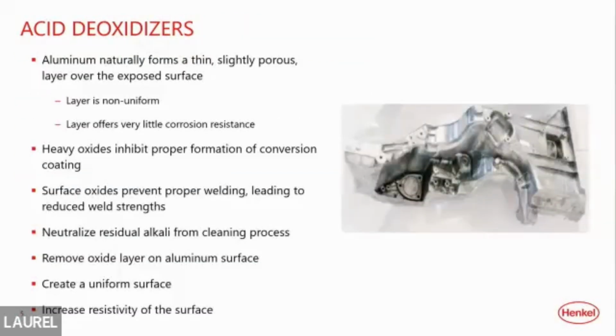Now, then we move on to the acid deoxidizers. This is very important. So we have a shock tower here with all different profiles and all different levels of oxidation. So now for acid deoxidizers, we're going to be removing the aluminum oxide layer. Now, that aluminum oxide layer is a pain because if you don't remove that and you glue it or put paint on it or put a weld on it, that aluminum oxide layer is very brittle and it will just fail.